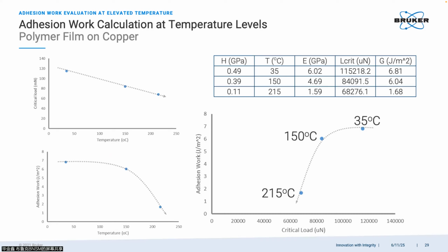But if you take a look at the Gibbs energy changing with temperature, it's very different, because your hardness and modulus also change dramatically with temperature. So we can see there are two different slopes. One is below 150 degrees Celsius, where the interfacial energy is not decreasing that much, but when the temperature goes up to 150 degrees Celsius, the interfacial energy drops very significantly.